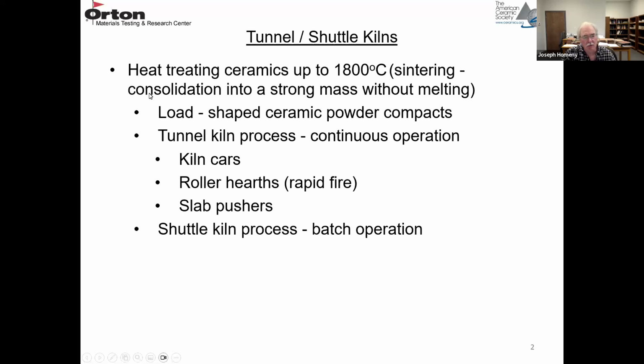Basically, the sintering process is a consolidation process producing a strong ceramic without reaching the melting points. So these furnaces go up to about 1800 degrees C, and basically they're firing ceramic powder compacts of some type and going through the sintering process. The tunnel kilns are continuous, and the shuttle kilns are a batch operation.